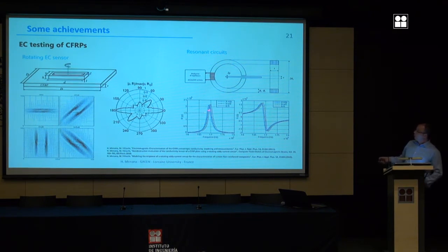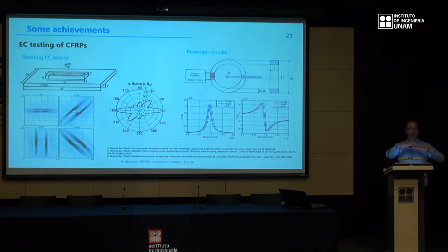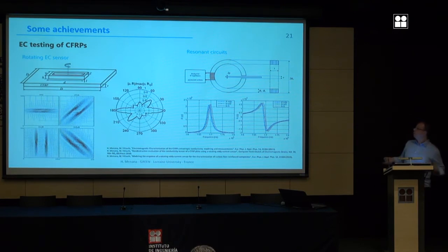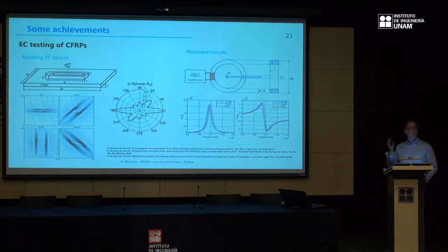So we measured the variation of the impedance of the ferrite core with respect to the ply varying in the ferrite core. This is the response. You have here the response when the fibers are in these directions, and another response when the fibers are in the perpendicular directions. So this is used also to characterize the conductivity, parallel and perpendicular to the fibers.